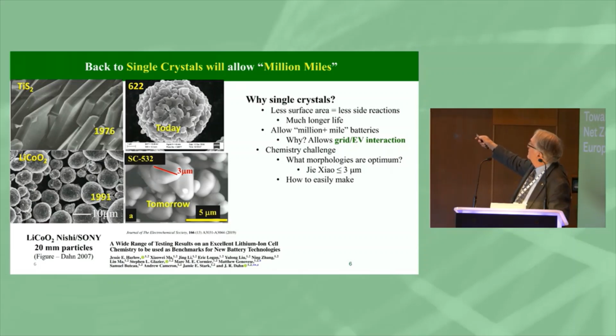So these are about 200 nanometer primary particles. These secondary particles are about 10 microns across. These work very well, but they're obviously very reactive. So you can get a lot of power out, but if things go wrong, you can get a lot of bad things happening too. So there's been a push for the last 3 or 4 years, initiated mostly by Jeff Dahn, to go back to the beginning, back to single crystals. So we reduce the surface area and reduce the reactivity.